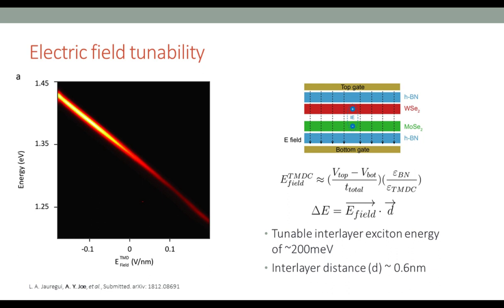We are exciting with the 660 and collecting the PL energy while applying an electric field. We apply a voltage on the top and bottom gate, and from this we can generate an electric field. What we find is that we can tune this energy by almost 200 meV. So now we have a 200 meV tunable NIR light source, and from this we can extract a dipole moment. The electric field times the dipole moment is the shift in energy for the first order Stark effect, and this agrees quite well with the expected interlayer separation, which is around 0.6 nanometers.